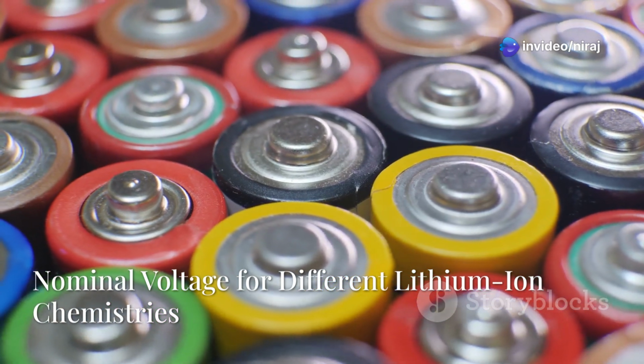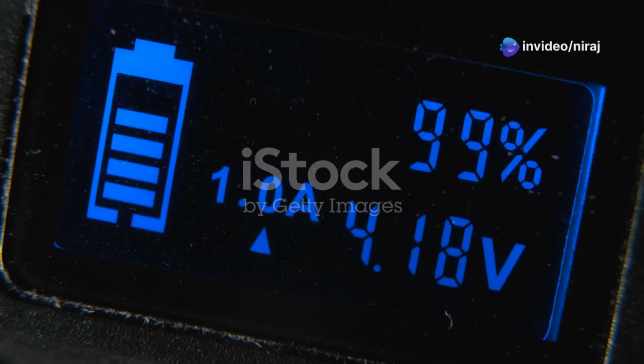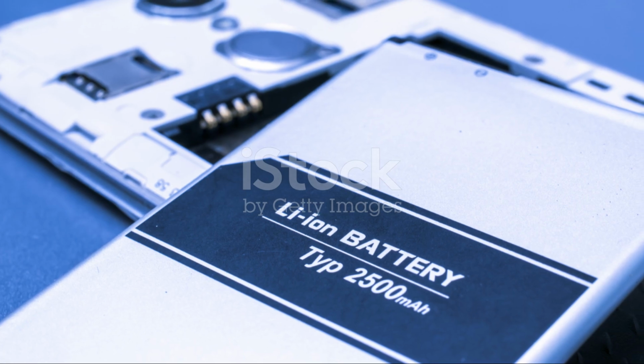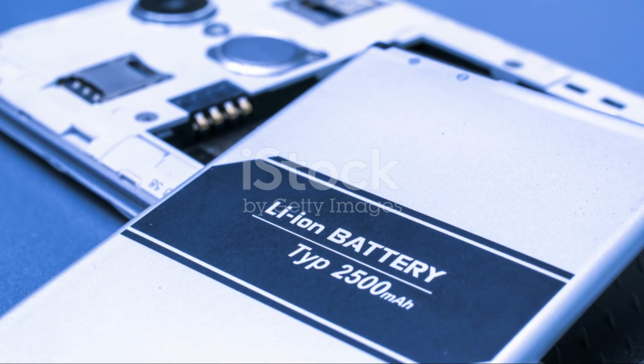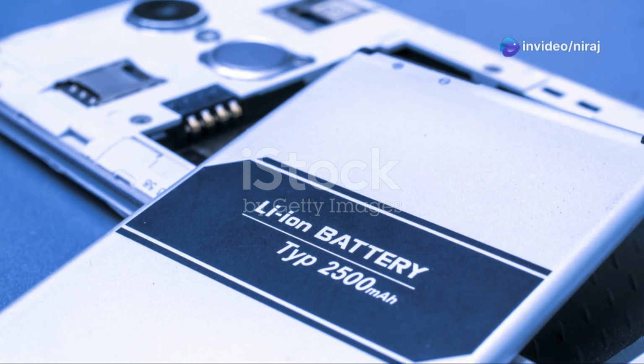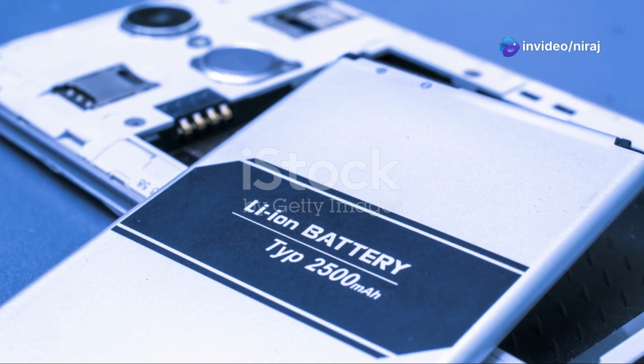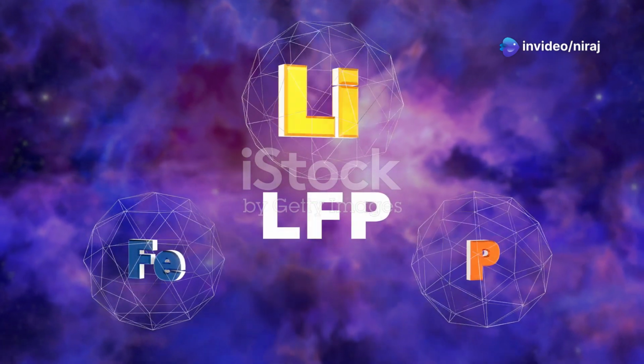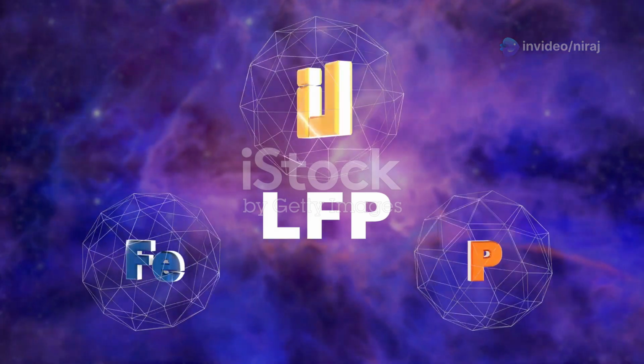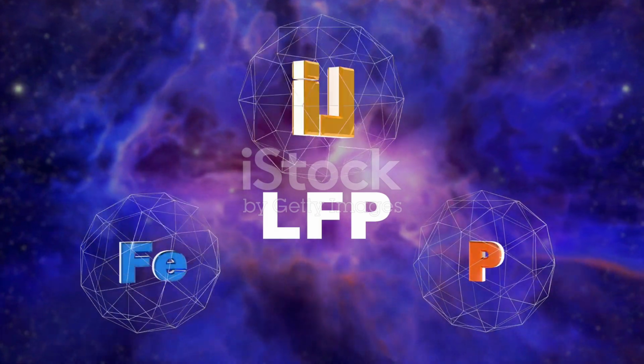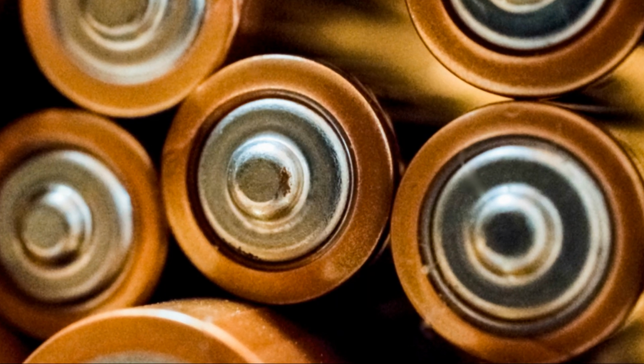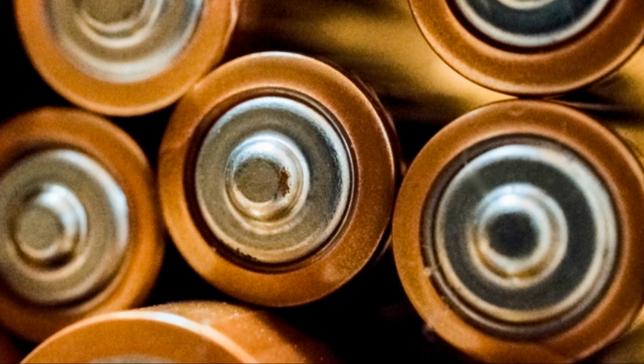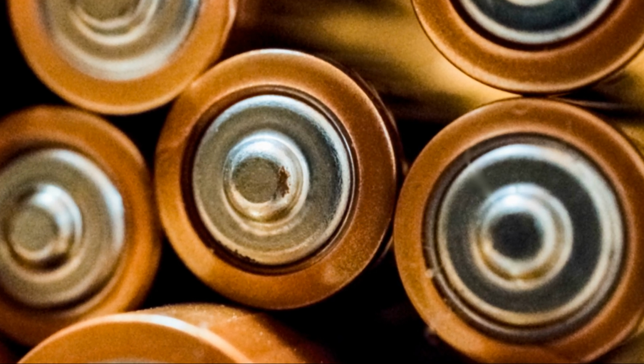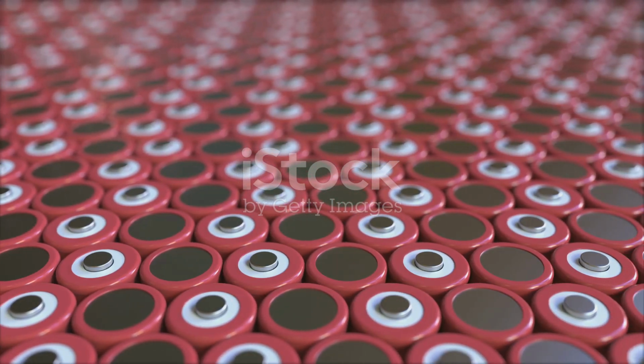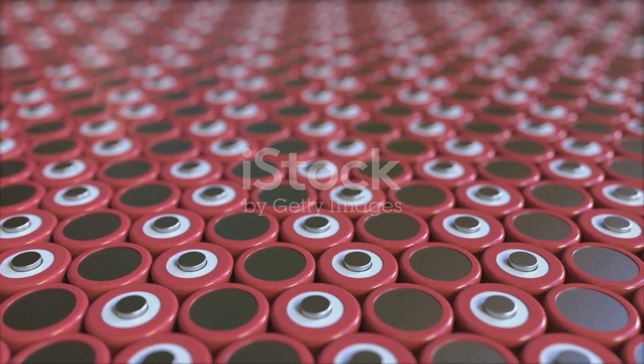Nominal voltage for different lithium-ion chemistries. Battery chemistry, nominal voltage, fully charged, cutoff voltage. Lithium cobalt oxide, or LCO: 3.7 volts, 4.2 volts, 2.8 volts. Lithium iron phosphate, or LFP: 3.2 volts, 3.65 volts, 2.5 volts. Lithium nickel manganese cobalt, or NMC: 3.6 volts, 4.2 volts, 2.5 volts. Lithium titanate, or LTO: 2.4 volts, 2.8 volts, 1.8 volts.